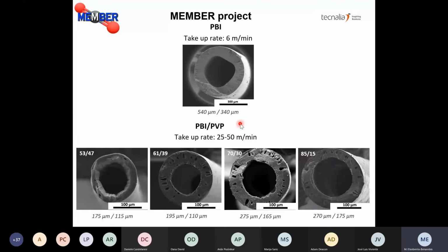And so we prepared PBI-PVP blend fibers at different PBI-PVP ratios, and by the addition of PVP, the as-spun fiber elasticity increases a lot. So we managed to prepare fiber at a take-up rate as high as 25 to 50 meters per minute. And as you can see, this results in a significant reduction in fiber diameter.